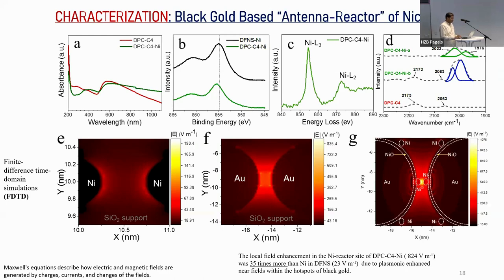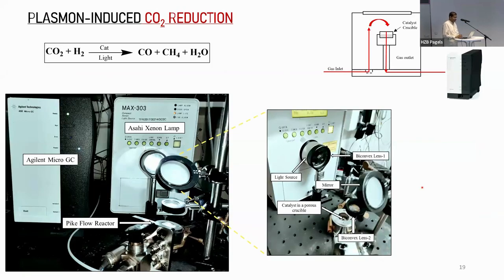So based on these basic characterizations, we went ahead and carried out the CO2 reduction reaction. CO2 plus hydrogen using solar light, you get CO, methane, and water as a byproduct. It's a flow reactor. We use a xenon lamp, which has a spectrum very close to sunlight, and you can have some filter, and you have a micro GC connected online to monitor the products. This is where we keep our catalyst, and the light is coming from the top. Gas goes in, interacts with the catalyst under exposure of the light, and the product is then monitored by GC, as well as the liquid product.